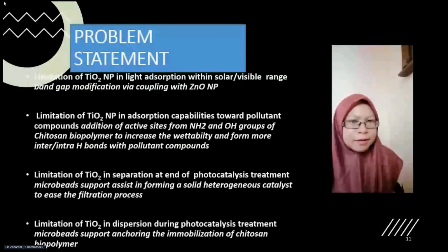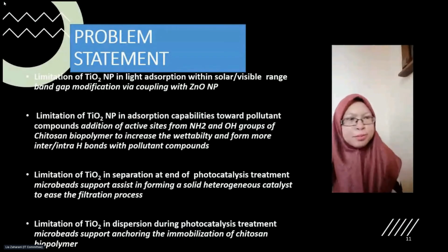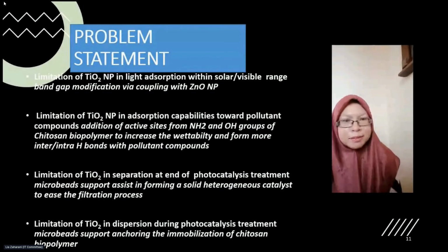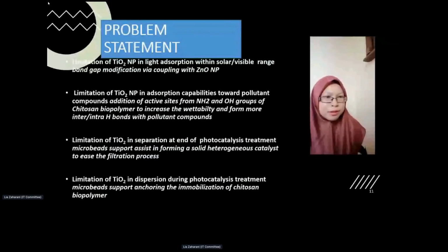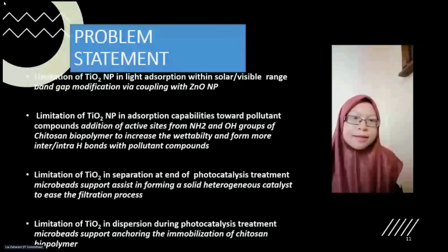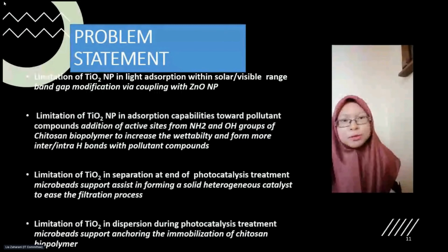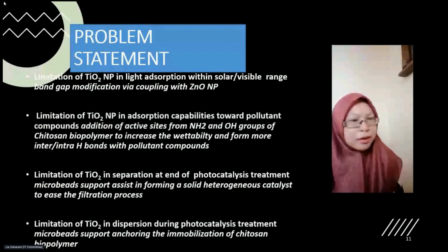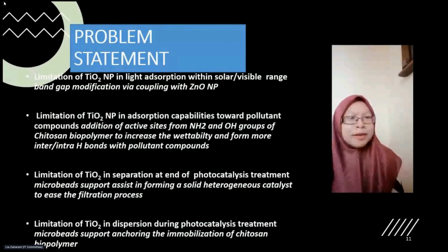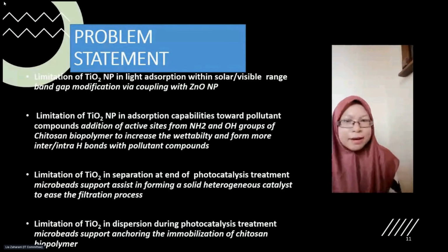And here, chitosan is used as a support material due to the presence of the amino and hydroxyl groups, which serve as the active sites capable of enhancing the adsorption properties of the hybrid catalyst. The particle size and morphology of nanoscale photocatalysts are also a problem in full-scale water and wastewater treatment because the particles should be removed or recovered after the treatments. To address this problem, chitosan-based particle composites have been produced as microbeads, which can be filtered out by a simple filtering process at the end of the treatments.